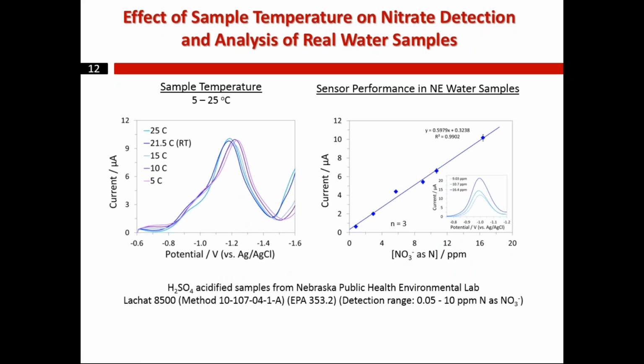Another factor that you have to consider is the effect of sample temperature. Again, if you think of the water samples that you're analyzing in the real world, the temperature of water in these samples might be different. So we had to make sure that this sensor can be used for detection of nitrate in a variety of temperatures. And here you can see the result that we got for keeping the concentration of nitrate constant and varying the temperature of the sample. And as you can see, we almost observed that the response of the sensor toward concentration of nitrate is independent of temperature of the sample.